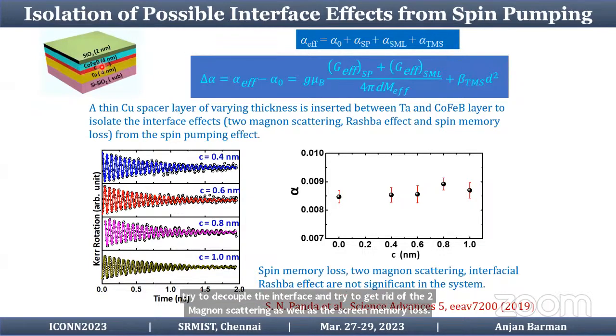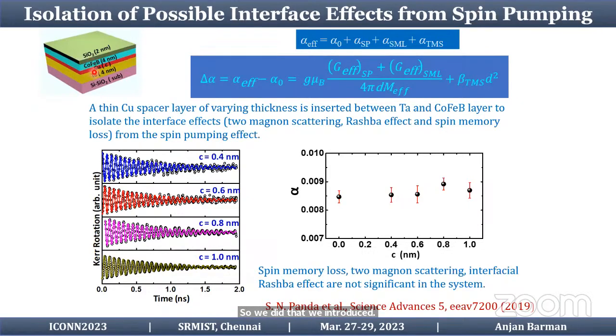So we did that. We introduced a copper spacer layer between cobalt iron boron and tantalum to decouple the two layers. And in this case, we increased the copper layer thickness. In principle, if the two magnon scattering and the spin memory loss were to be present, then we would see a variation in the damping as we increase the copper layer thickness.